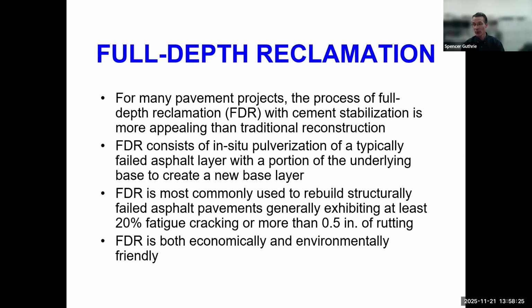And so with that motivation, I introduce a full depth reclamation process that can be very advantageous for many pavement projects. In fact, the process of FDR, full depth reclamation, with cement stabilization is becoming more appealing than a traditional reconstruction approach. FDR consists of the in situ pulverization of a typically failed asphalt layer with a portion, might be all, might just be a part of the underlying base to create a new base layer. FDR is most commonly used to rebuild structurally failed asphalt pavements, generally exhibiting at least 20% fatigue cracking or more than ½ inch of rutting. Under those criteria, a roadway might warrant some full depth reclamation consideration. It's both economically and environmentally friendly.